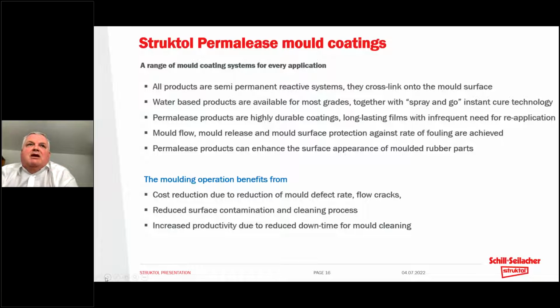Yeah, so to summarize really what we have, Permalease semi-permanent reactive systems, our Permalease range are cross-linkable systems. They cross-link onto the mold surface during the heating of the mold. Water-based products together with spray and go instant curing are very much to the fore of the technology. Coating can be very durable, so you can get long-lasting films with a reduced need to reapply. Mold flow, release, and mold surface protection are all key attributes that you could consider when using a mold coating. And indeed, it's also possible to enhance the surface appearance of rubber parts by using such coatings. Next slide, please.